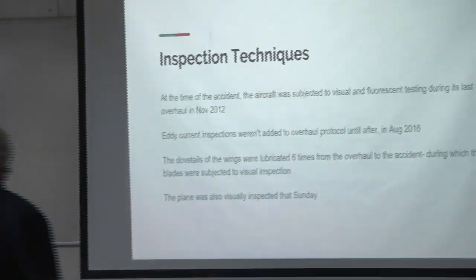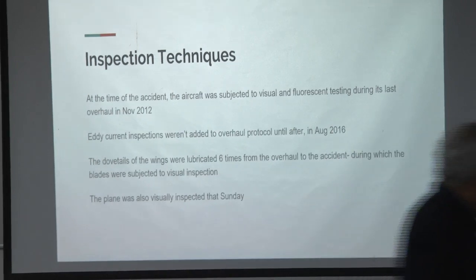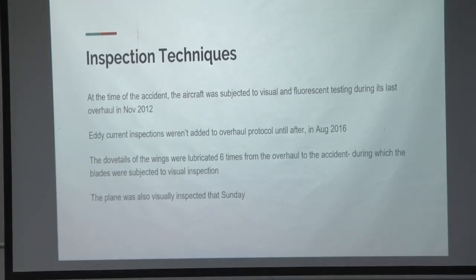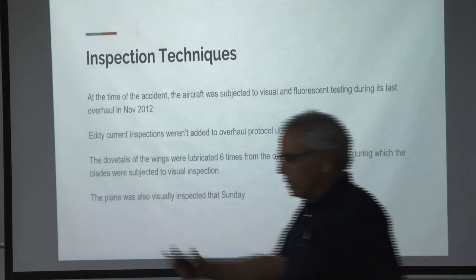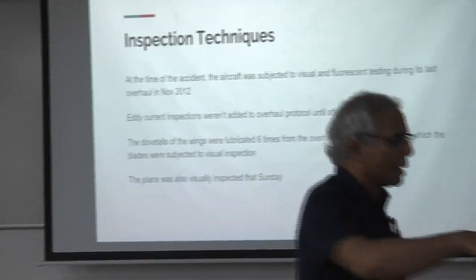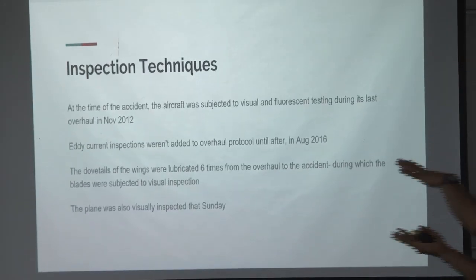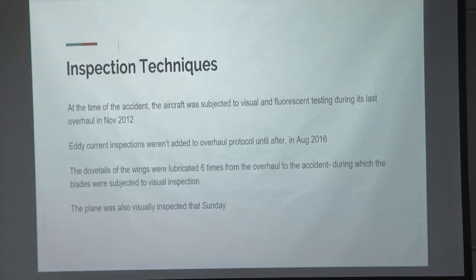So you always lubricate those surfaces to reduce the friction. In this case, we use moly disulfide. It's a solid lubricant for engines, because it's very stable up to high temperatures. So they were lubricated to take care of any fretting fatigue. And also the plane was visually inspected. Every time the pilot lands the plane, and before taking off, they walk around the plane and see if they can see any big cracks, because you can fly a plane with a crack this long as long as it's not in the fuselage.